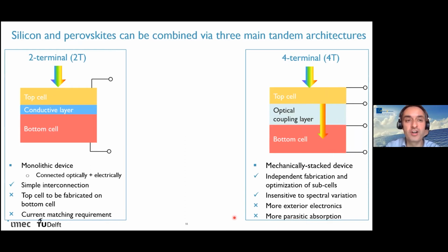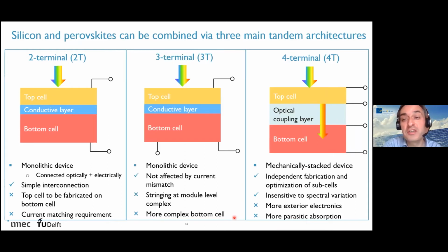These are the 2 main routes being investigated. But there is also something in between called the 3-terminal device, which is still a monolithic device. You grow the top cell on top of the bottom cell, but you have a 3rd terminal in the bottom cell, which allows you to bypass current matching. So in this case, you don't need current matching. The idea of the 3-terminal device is to combine the best of both, but the challenge is that you might also end up with the problems of both combined. These are the 3 device structures typically being investigated.